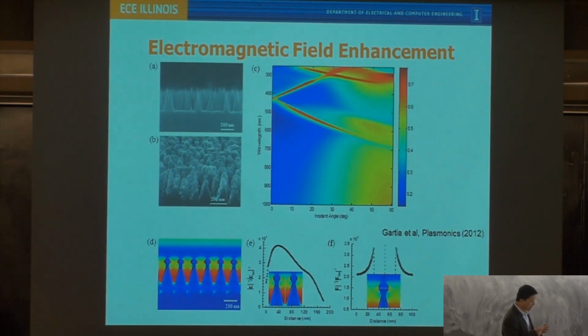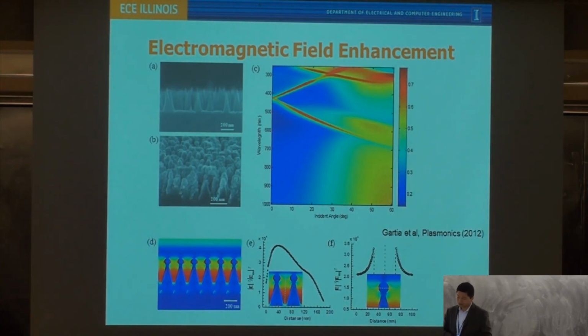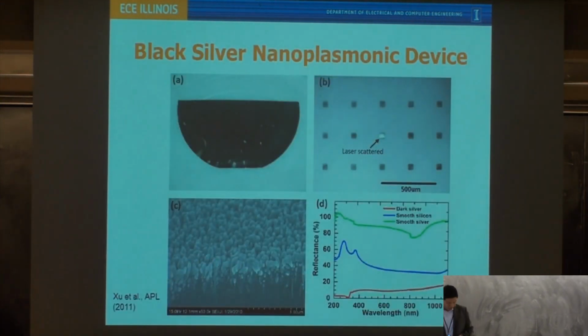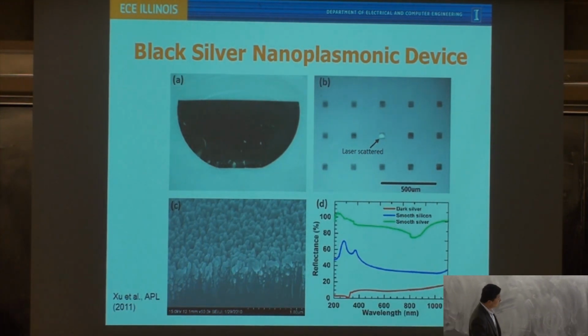But what we want to do is basically have a relatively broadband enhancement to the fluorescence. So we started creating a non-uniform structure, where the size of the cones are quite similar, but the arrangement of them are not in order. Okay. So to make the device, we can also make a large areas. So here is showing a half wafer, and the diameter is about 100 millimeter. So we can make a lot of those cones on the surface of a large area substrate.